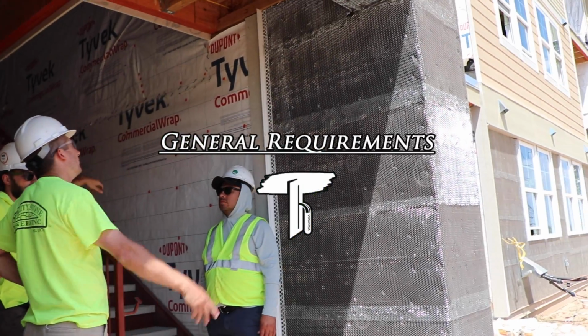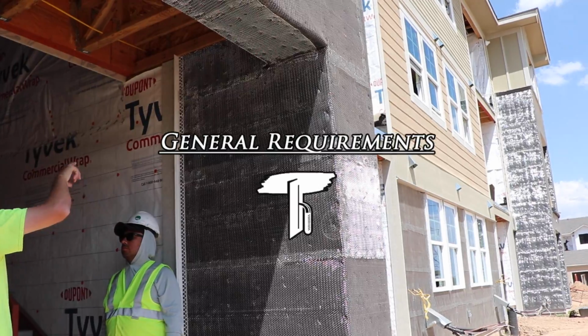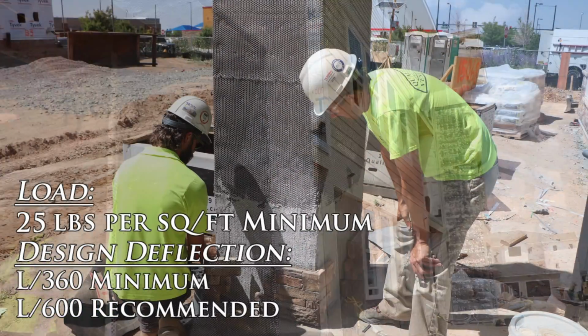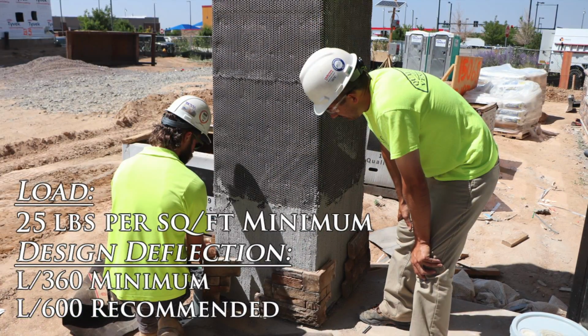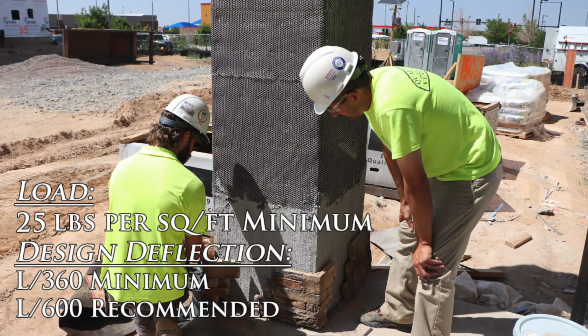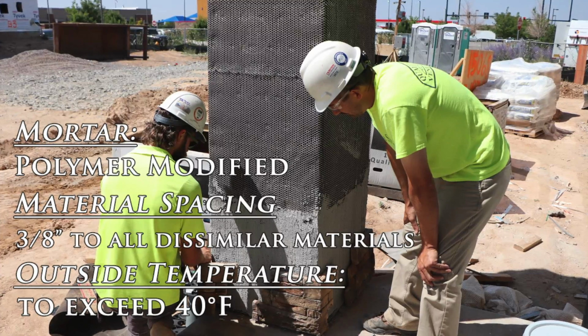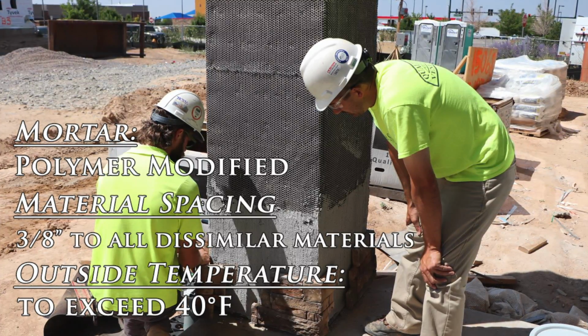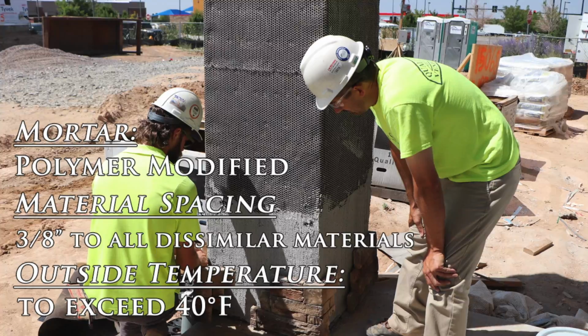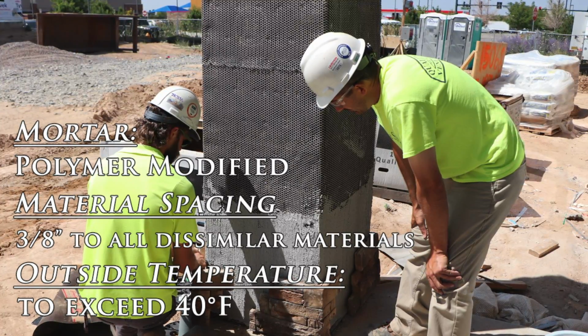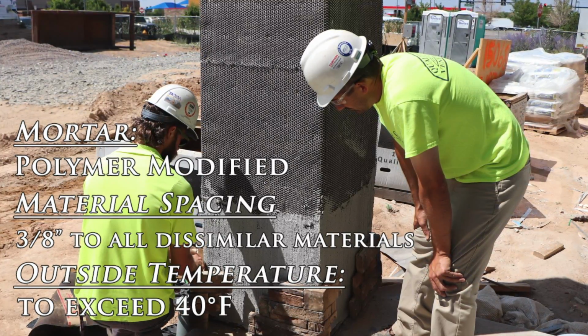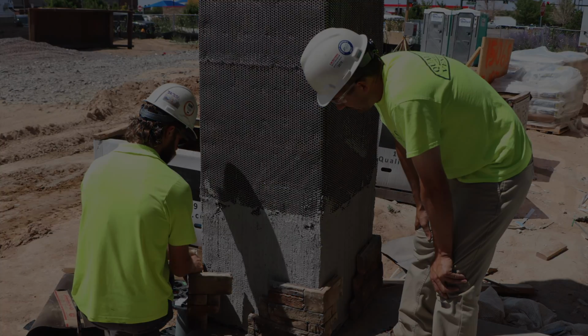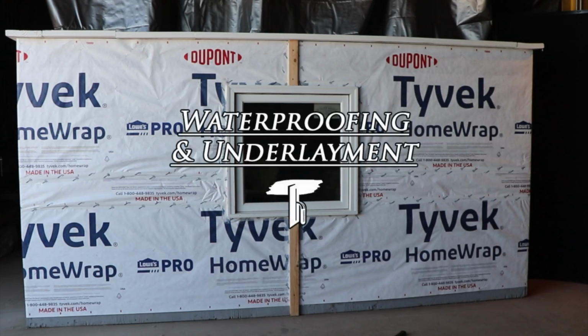General requirements. The substrate is required to be rated to support 25 pounds per square foot minimum. A minimum building design deflection of L over 360 is required, with a design deflection of L over 600 being recommended. Polymer modified mortar is required for scratch coat, applying the stone, and grouting the stone. Stone is required to be gapped from all dissimilar materials by 3/8 of an inch to allow for expansion and contraction, and outside temperatures must exceed 40 degrees Fahrenheit. The NCMA installation guide should again be followed for all underlayment procedures and material requirements in your area based on the wall type.